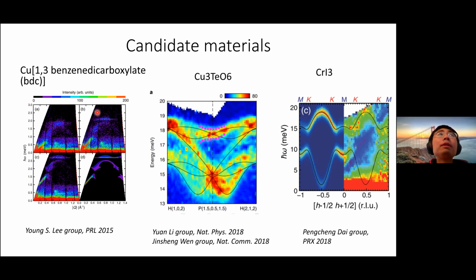For these materials, the experimental probes that measure them are mostly neutron scattering spectroscopy. So what people do is first build theory models for the spin wave dispersions in the system, and then inelastic neutron scattering spectroscopy can serve as a direct probe for this dispersion of the magnon.